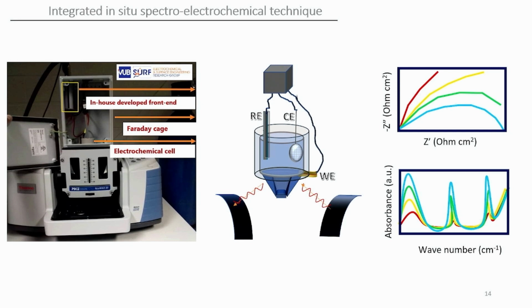Now we go one step further. In the case of organic coatings, we now combine these ORP-EIS measurements with the so-called in situ infrared system, where you come with your beam from the back and where you have your metal placed as a PVD coating on an optically transparent crystal. Out of that, we can measure the in situ infrared at the interface, and in the same time domain, we apply the impedance measurements.